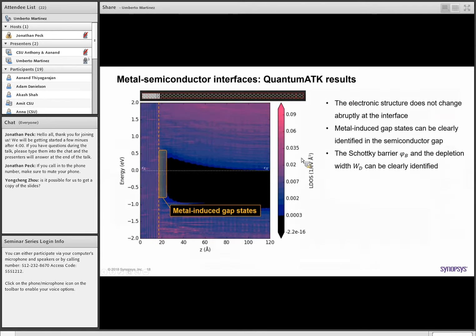And if we study that in more detail, we can see that now we have really atomistic results, meaning that we see this dashed line show the boundary between the metal and the semiconductor. However, we see that these metal-induced gap states propagate a few atomic layers into the silicon side. And then another key feature is this depletion region, which is captured very well by these simulations.